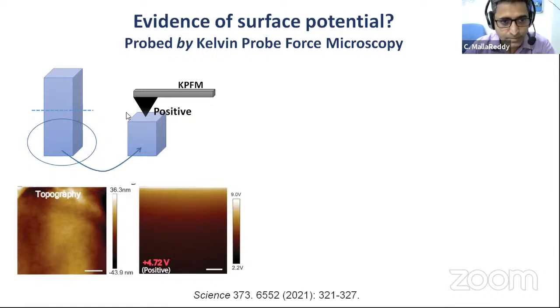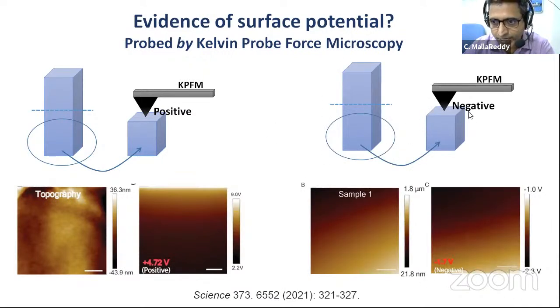So that means the surface is positively charged. Then we looked at more crystals, and on some crystals we found negative surface potential, and on some crystals we found positive surface potential. On these crystals we could not really determine the polar axis direction. Since we have not done the phase indexing before doing all these experiments, we don't know exactly the orientation along which you get positive charge and along which you get negative charge. But what is more important is that you have positive charge on some crystals and negative charge on others.